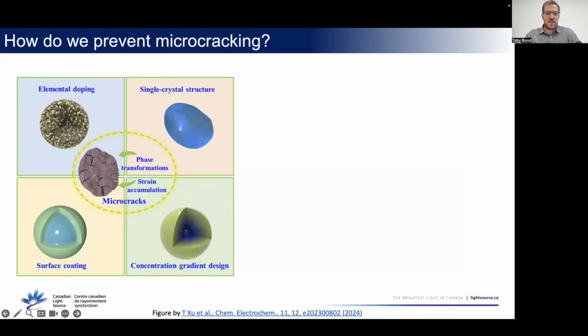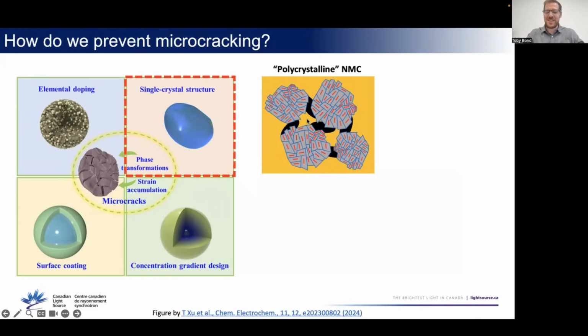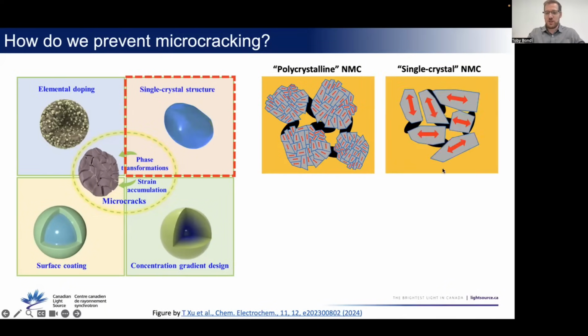Usually in the past, this has involved some kind of doping, adding something to the material to help stabilize its crystal structure, or applying some kind of coating that keeps it from expanding and contracting too much, or modifying the structure somehow. But I'm going to focus on this one particular type of material called a single crystal positive electrode. So what this is, these snowballs I was talking about before, in our technical jargon, we call this a polycrystalline material, and that's because there are many crystallites inside each particle. But a single crystal electrode has just one big crystal in a particle.